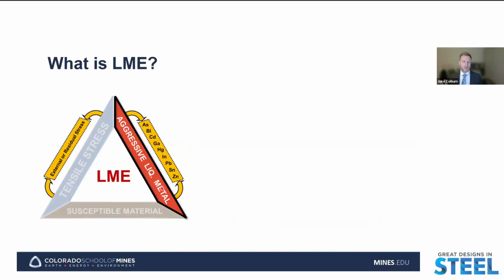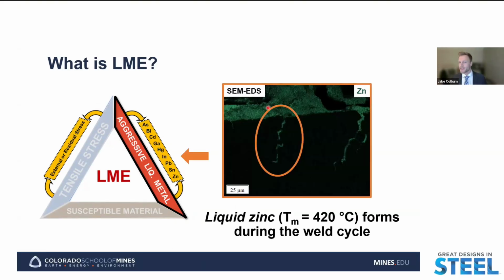More specifically, as we look at each of the three components that lead to LME, we can begin by looking at what aggressive liquid metal we are concerned with in this system. Again, that's liquid zinc, forming during the weld cycle as the temperature reaches above 420 degrees Celsius and zinc can melt. Then as temperatures continue to rise, we can get penetration of the zinc into the substrate, as we see here with this zinc EDS map. So that's our aggressive liquid metal.